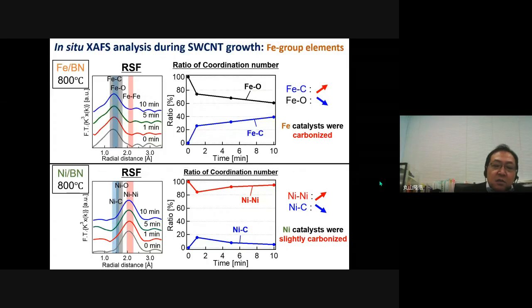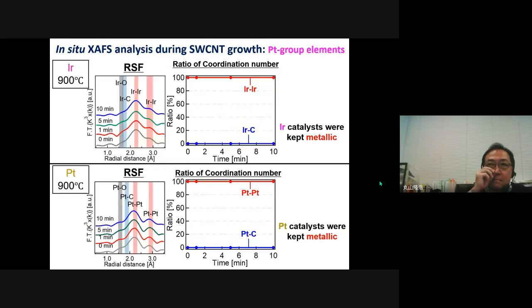For nickel catalysts, they were reduced to metallic during temperature rise. And the chemical state of nickel was mainly metallic, but slightly carbonized during nanotube growth. Next, please. These show RSF and the ratio of coordination numbers of iridium and platinum catalysts during carbon nanotube growth. In the case of iridium and platinum, the chemical states were almost metallic. Next, please.